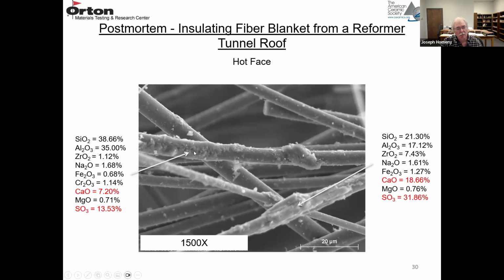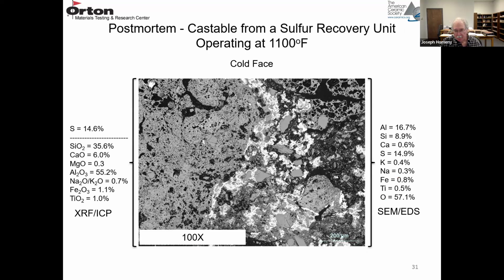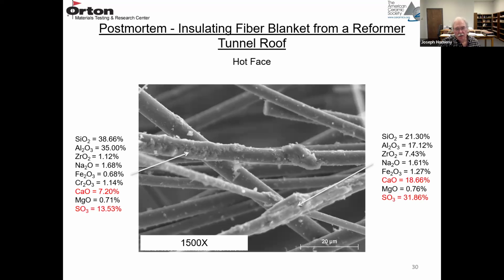The way the SEM looks at these materials, there's a certain zone that the electron beam reacts with, and you're picking up alumina, silica, and zirconia below the contamination. But it's mostly CaO, and the software picks out SO3. So there's quite a bit of calcium sulfate on the surface. So that was an example of a fiber material becoming contaminated, and eventually that will degrade.